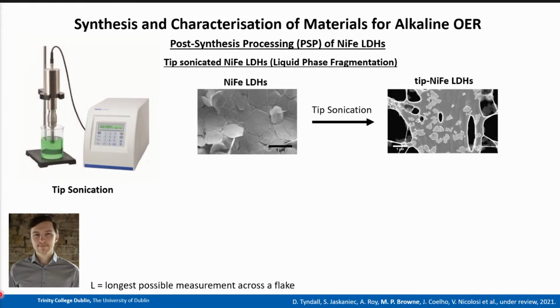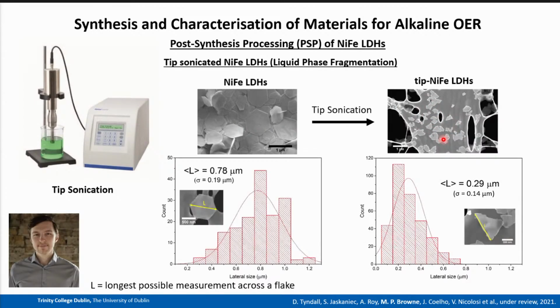So essentially, Daria used tip sonication methods to fragment the lovely hexagonal shapes that you have into these shapes that you see here. Daria was then able to use the SEM images and a software called ImageJ to determine the sizes of these materials. So L, when you see L anywhere in this presentation from now on, that is the longest possible measurement across a flake. So when we look at the size distribution of the as prepared nickel iron LDHs to the tip sonicated ones, we can see that there is a massive decrease in the size of the tip sonicated materials.